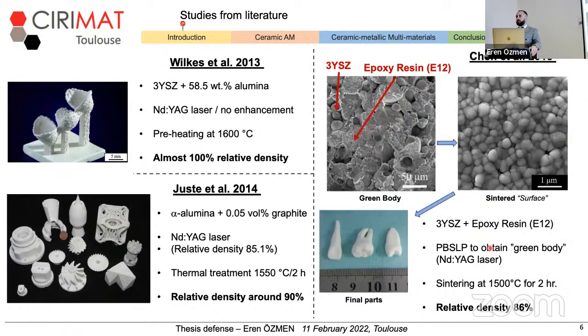In another approach applied by Chen et al., ceramic powder was mixed with epoxy resin, and PBSLP was used only to process the polymer inside the mixture to create green bodies. And then to sinter the particles which were embedded in the polymer, a post-sintering process at 1500 degrees for 2 hours was applied, and pieces with a relative density of 86% were obtained.